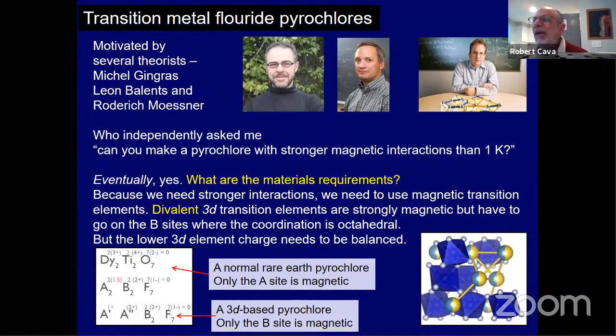And you have to realize that if you have a rare earth, the interactions are going to be very, very low. The effective magnetic interactions will be low because these are f electrons, which are close to the core of the atom. And so they're not going to be good for interacting with each other.